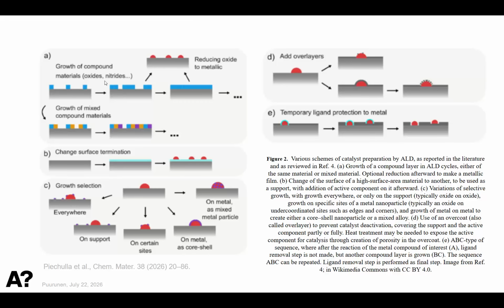And this is how the very first examples from Finland were. There was nickel grown from nickel acetylacetonate, I think, and then oxidation with oxygen at higher temperature, and those were reduced to nickel on alumina and then tested for hydrogenation reactions. You can also grow a wide variety of mixed compound materials, and this is how they started in Leningrad. They had the different vanadium and phosphorus and titanium and so on that they were mixing from early on in a pretty elegant way.